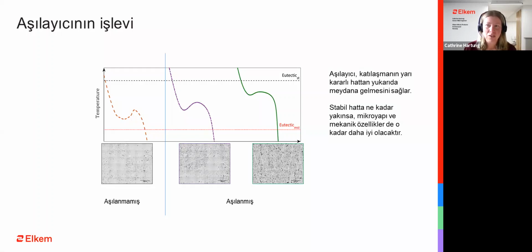So the job of the inoculant is to ensure that the solidification occurs above the metastable line. And the closer it is to the stable line, the black dotted line, the better the structure will be. Now here you see an example from our lab in Kristiansand, where we have 4 different irons. So the first iron here is uninoculated, and it's gray iron.